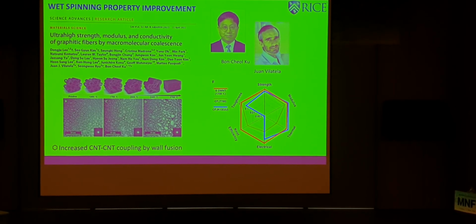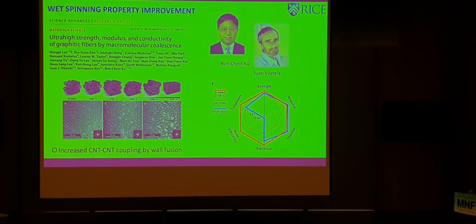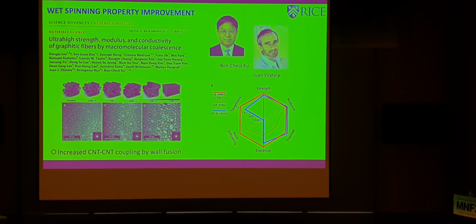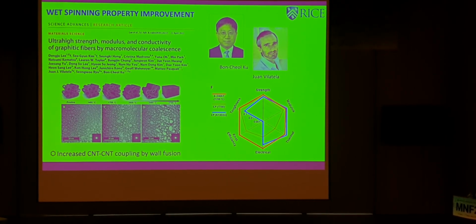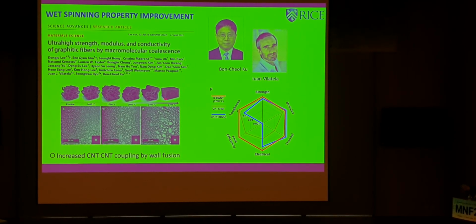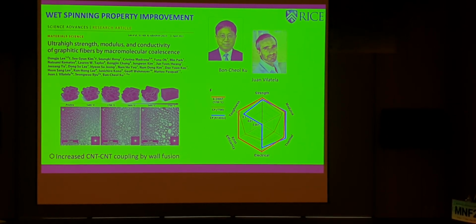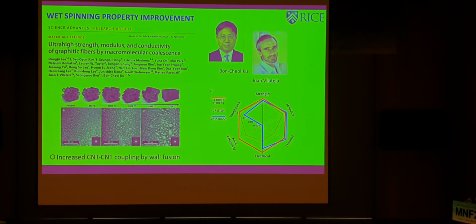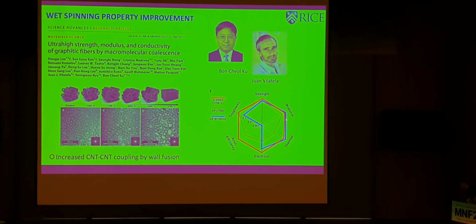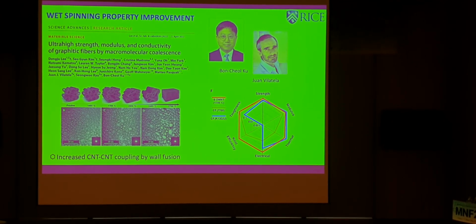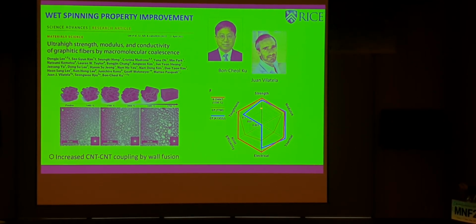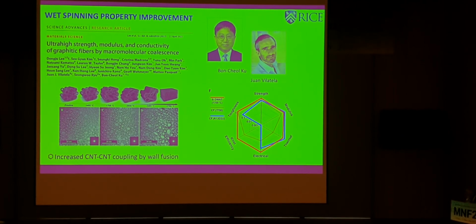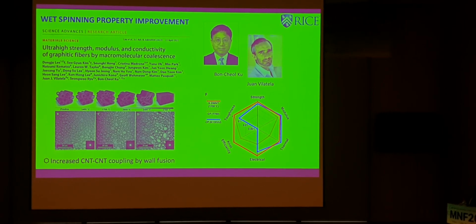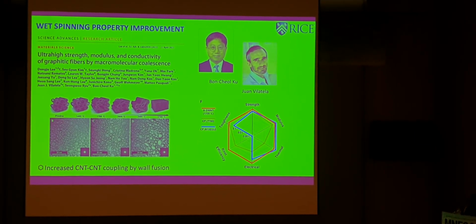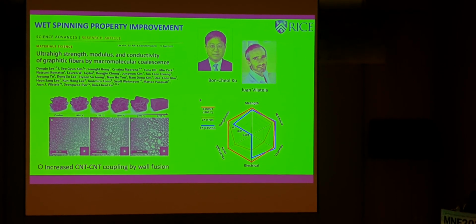Ben Cheol Ku and his team with Juan Villatella showed that you can take wet-spun fibers and make them even better by cross-processing. By getting to high temperature, you can get the walls of the fibers to fuse, and you can get this material that has really high properties. My contribution to this paper was the spider plot, that's all. But I see a lot of people are using the spider plots now.